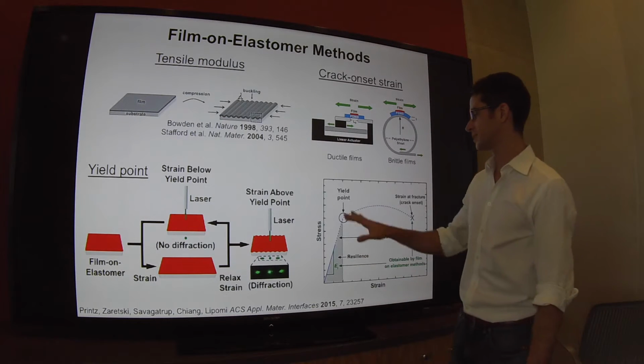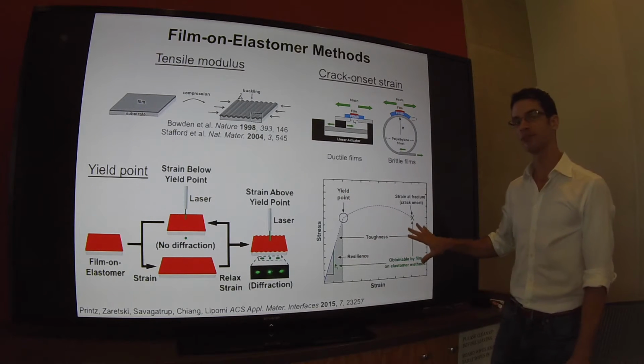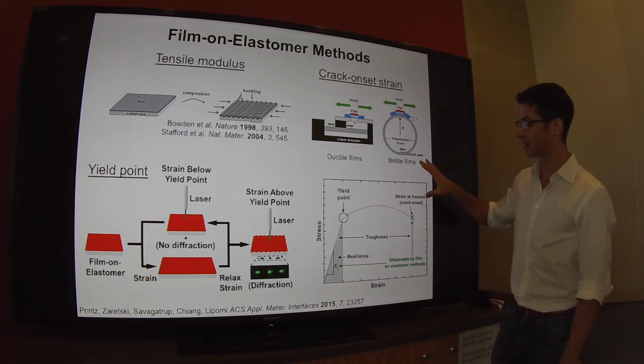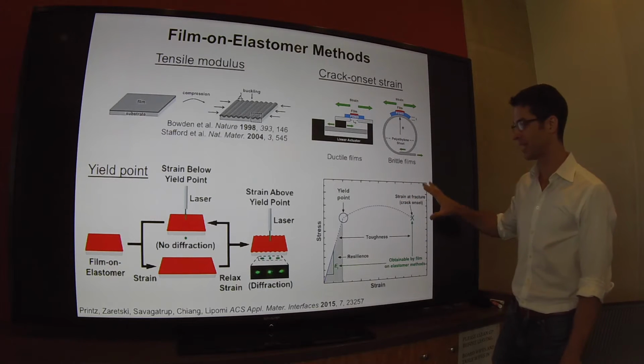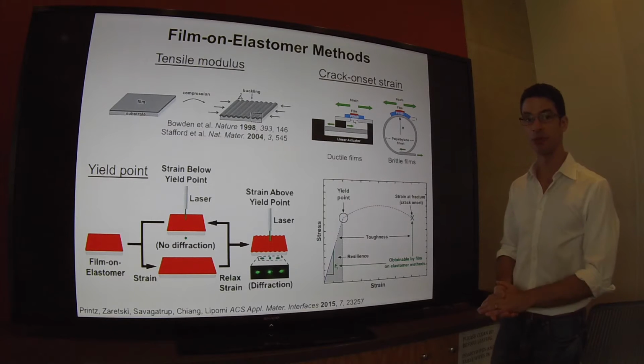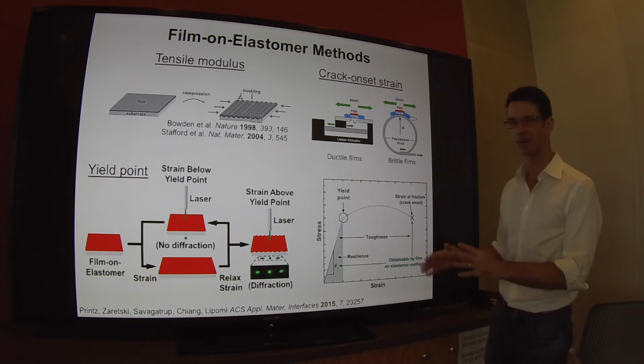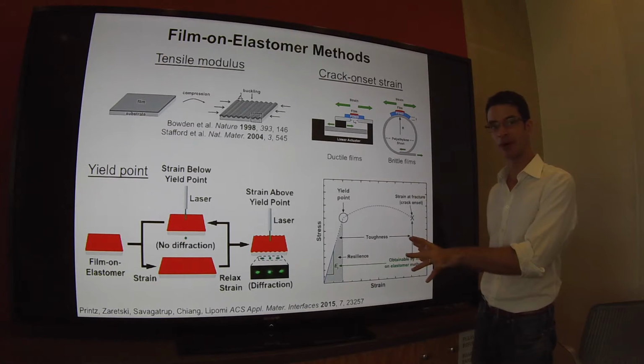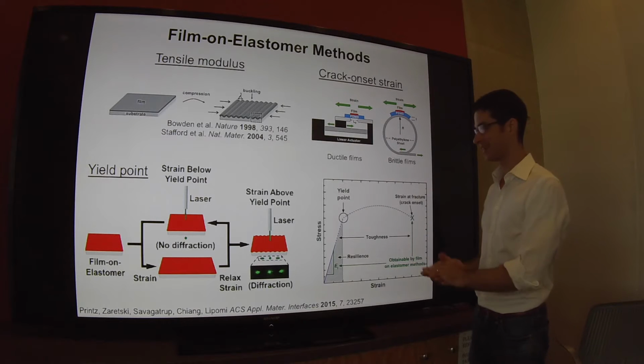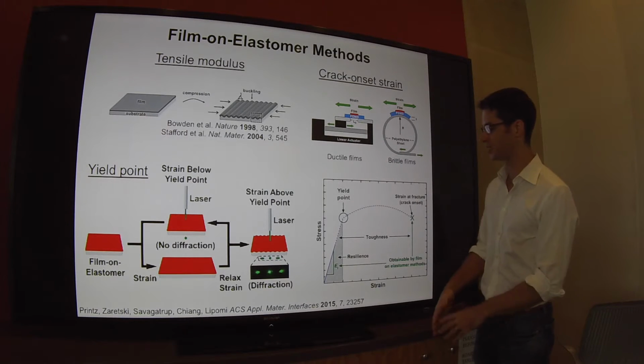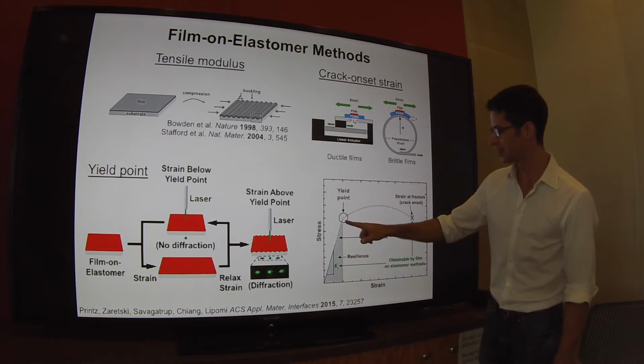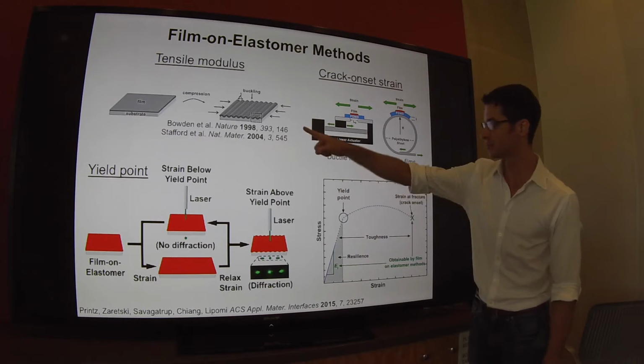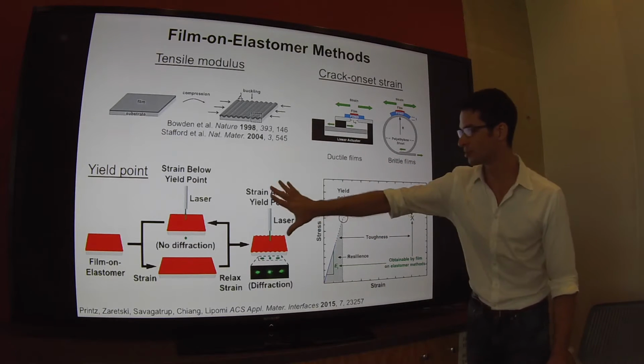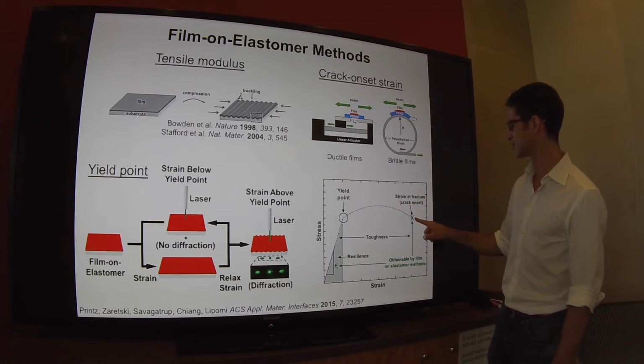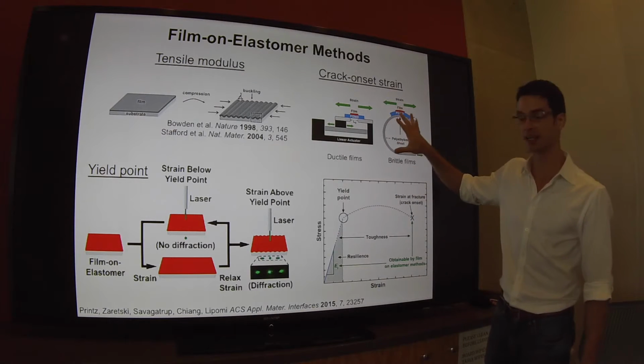Now we can put all of this information together to generate a rough sketch of the pull testing behavior, or the behavior that you would observe normally by pull testing. Now you're not going to get this exactly right, but you can at least get the principal features. So the slope in the elastic regime is the tensile modulus. The yield point is determined using this technique, and the strain at fracture is determined by the crack onset strain.